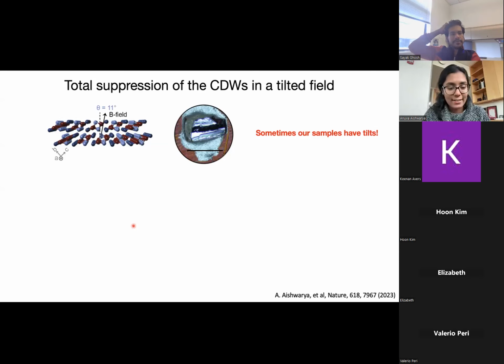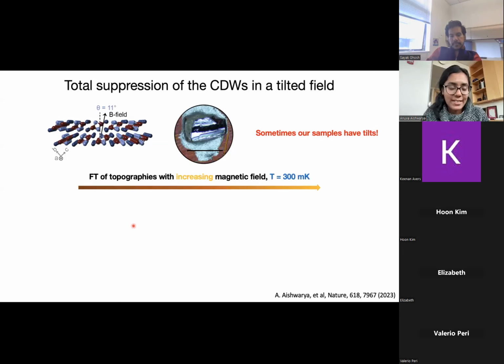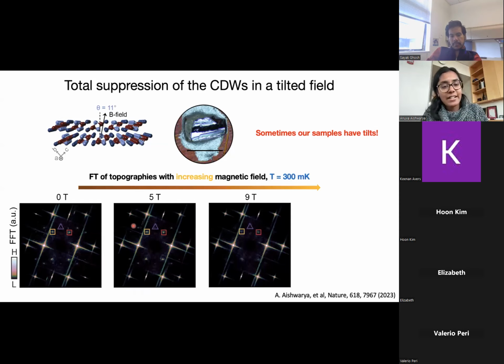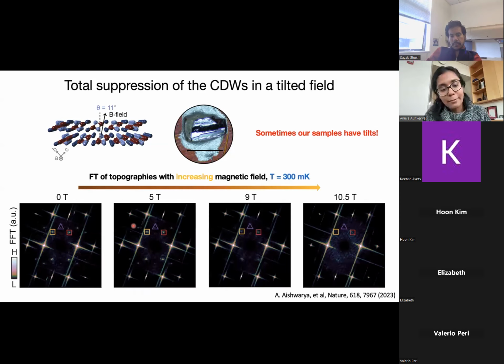So on one such sample, when we apply a magnetic field, what we see is that as we increase magnetic field below TC, all 3 components of the CDW are suppressed. You can see that this is 0, 5, 9, and 10.5 Tesla. And by 10.5 Tesla, we can hardly detect the CDW. And we do not even detect it in density of states.